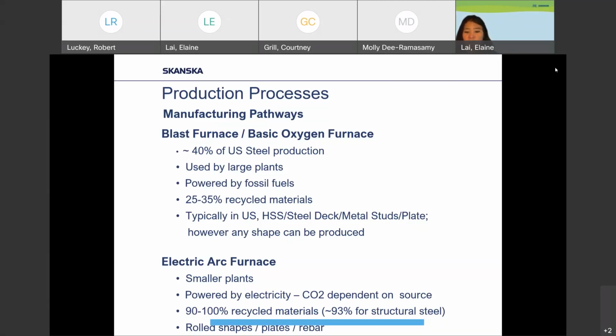The electric arc furnace, you're seeing a larger number of these plants in the United States starting to put in place EAF. They tend to be smaller plants, and they tend to also be powered by electricity. So the carbon intensity is largely dependent on where you're located and the grid mix in that location. Up to 90 to 100% recycled materials can be used in the electric arc furnace. On structural steel, you're seeing that average be about 93% recycled product. And the shapes that tend to be manufactured in these EAFs are rolled shapes, plates, and rebar.